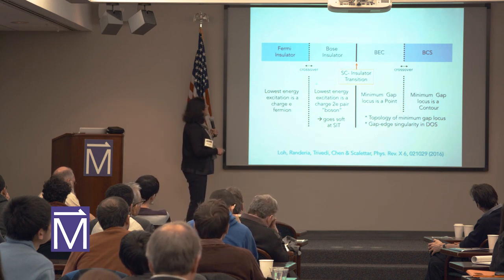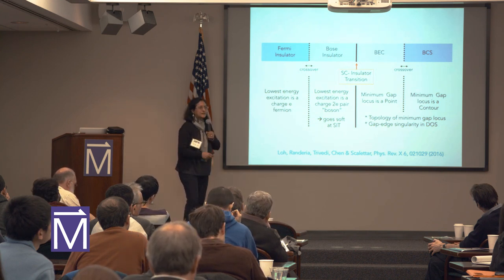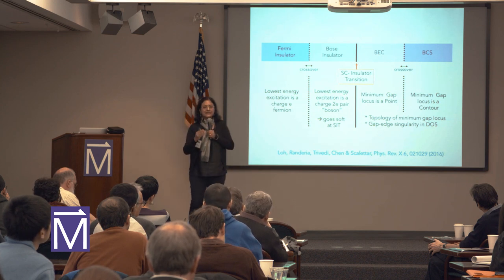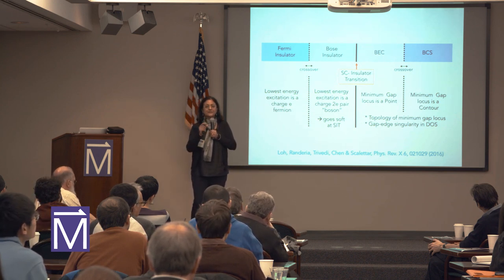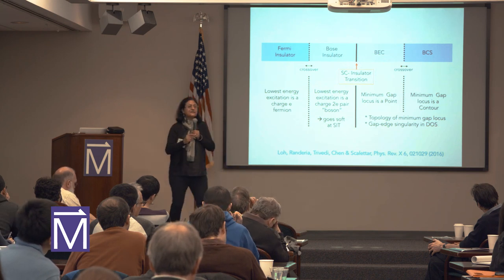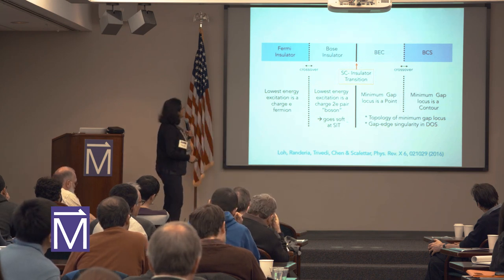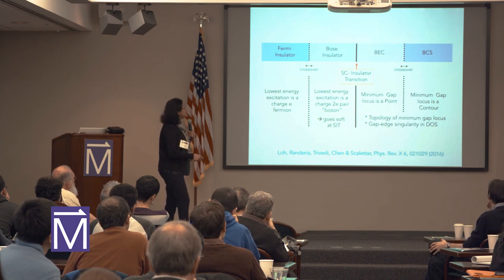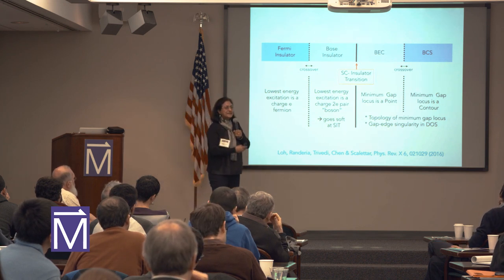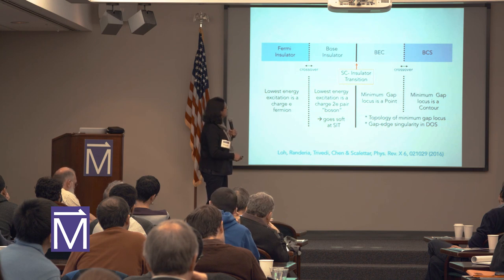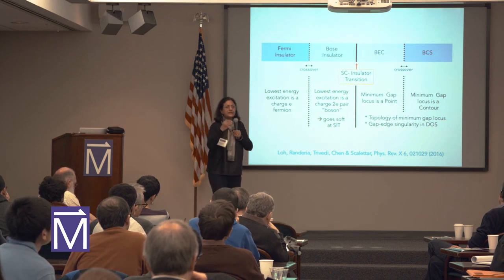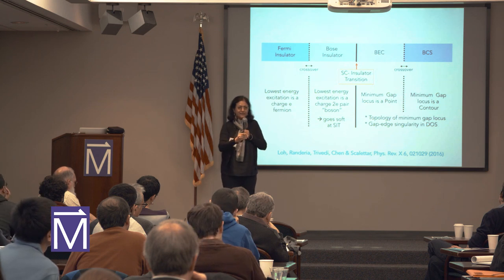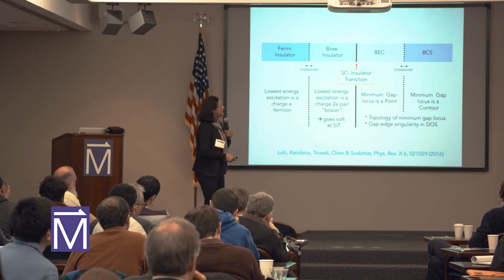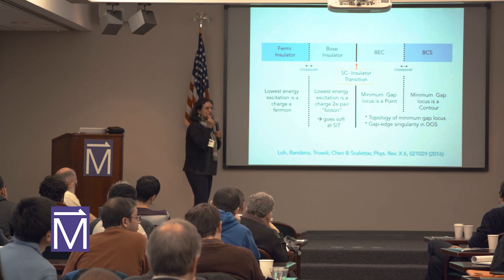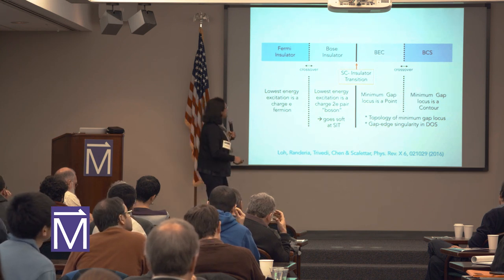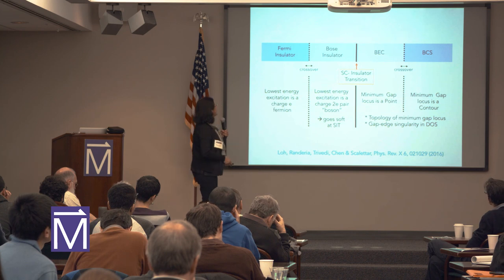So in other words, before an insulator becomes a superconductor, you should already be able to detect the signatures of pairs in the insulator. And this is a very strong statement. And then it's these bosons that would Bose condense into a BEC, and this condensation will happen in momentum space at the gamma point. And it's then another crossover from this gamma point BEC to a BCS superconductor as you change some parameter.